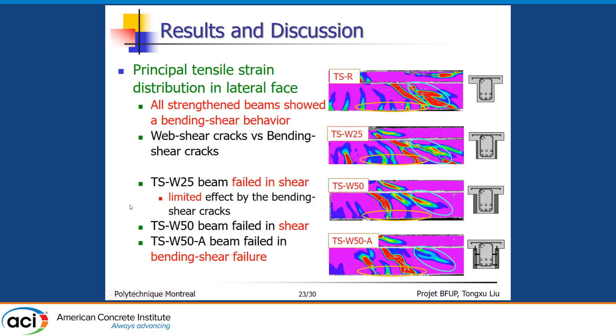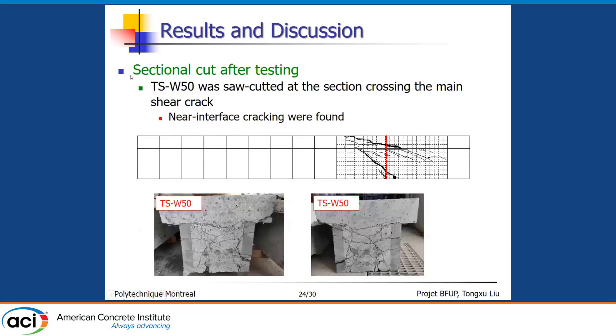To examine what is happening inside the beam, we conducted sectional cuts after testing at sections crossing the main shear cracks. We can see clearly the shear cracks across the section. We also found near-interface cracking in some areas, which may have an influence on the beam shear behavior.